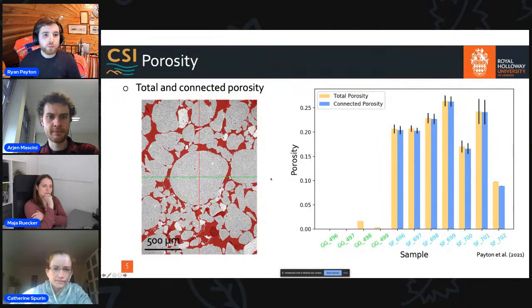So the first measurements which we can make are total and connected porosity. So here's a 2D slice. All of the darker phase, which is the pore space, has been segmented here using a mixture of automated and manual thresholding algorithms. So the total volume fraction here, we can see, is the total porosity in these yellow bars. All of these samples with lots of porosity are from the Sellafield site. So we can see there's lots of porosity present. However, in that cemented sample from Glasgow, very, very limited porosity.